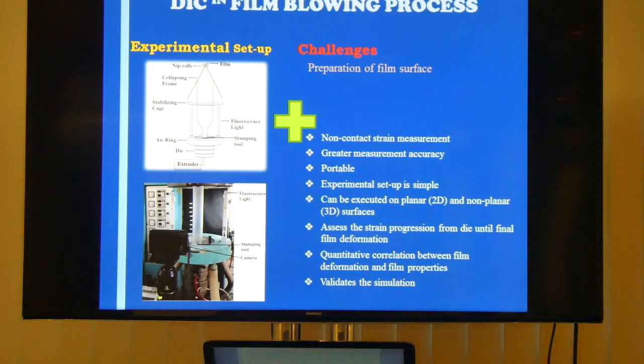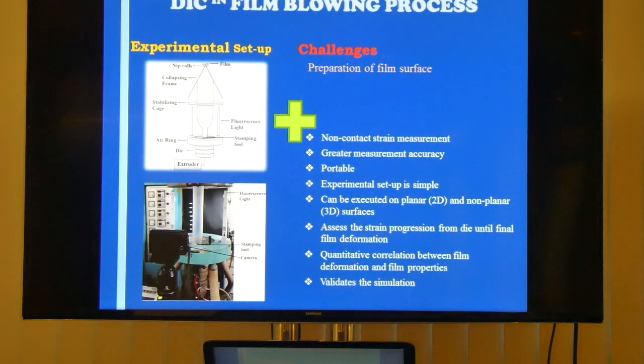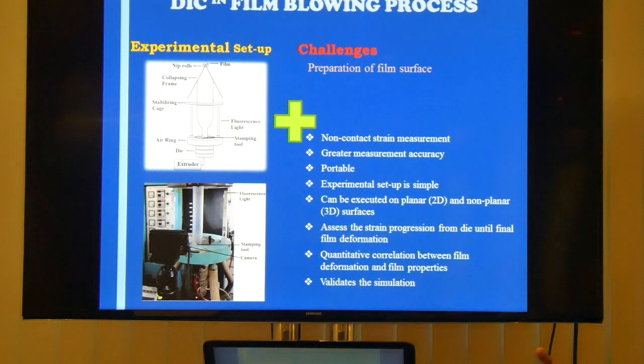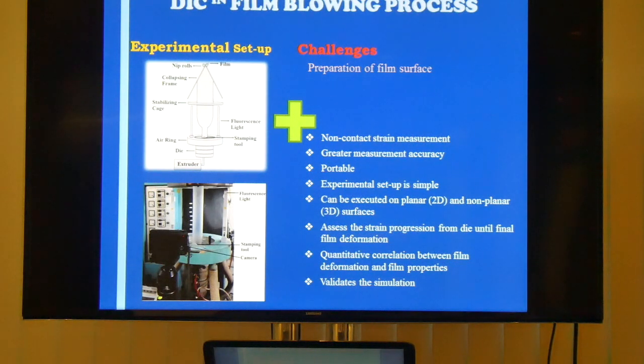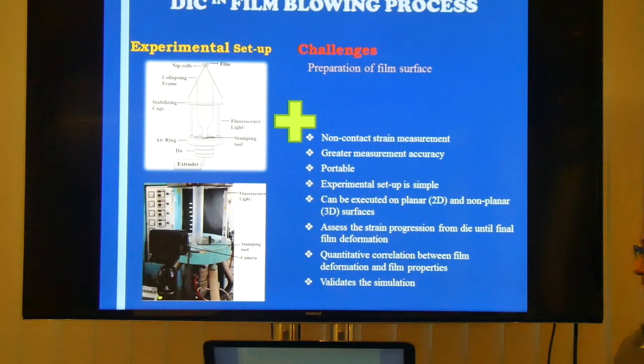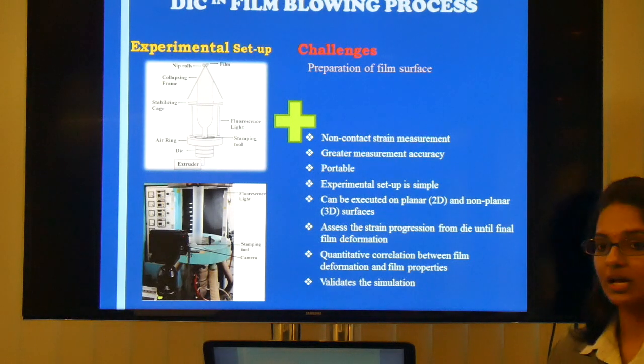The reasons for using DIC in the film blowing process are: it is a non-contact strain measurement that doesn't destroy the film surface; it provides greater measurement accuracy compared to other strain gauges; it is portable — the camera can be used anywhere and from any angle; it can be applied on both planar and non-planar surfaces, since our film is 3D and circular; it can access the strain progression from the die until full film deformation; and it will help us develop a quantitative correlation between film deformation and film properties, which can also be used for validation of simulation.